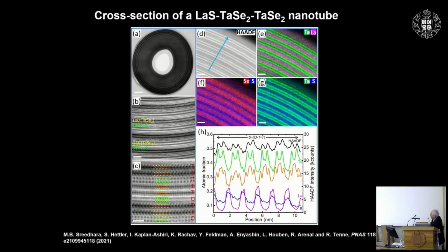the tantalum, and so we have a very beautiful graded structure, and you can see in the slicing with FIB that I mentioned how the tantalum binds to selenium mostly, and first of all, the tantalum and the lanthanum form a beautiful misfit nanotube structure, and then the selenium and the sulfur are absolutely different or segregated, although we work at 1,000 degrees C, and the entropy effect is much smaller than the enthalpy effect. So I think that with that I can conclude my talk.